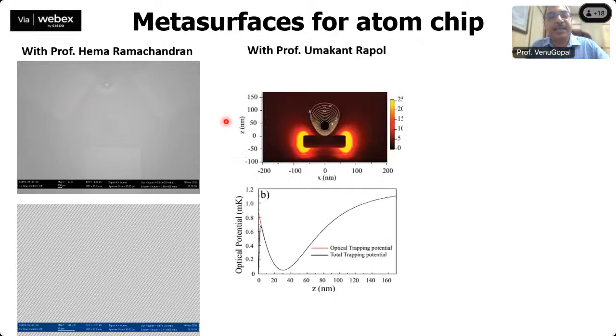We are also working on metasurfaces for atom chips. This work was initiated about 6-7 years ago with Professor Hema Ramchandran, who is unfortunately no longer with us. This is a simple grating structure. The gratings were designed in such a way that we launch light, and each of these gratings reflects one beam each, and these are about 3 to 5 mm away from the surface of the substrate, so we can make them co-focus together and use it for atom trap applications. We had certain issues with it. These structures were tested at DRDO, and we found some issues, and moved to other dimensions, other geometries, which I'll show a little later.